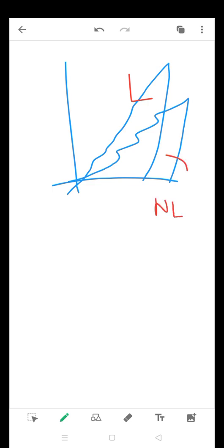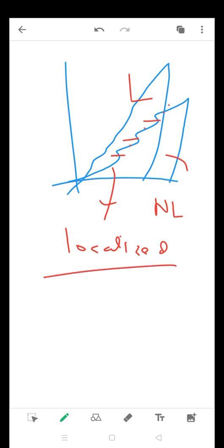So the difference that you can see between the two plots is that there are many more discontinuities or many more steps observed in the non-layered one, and these steps correspond to localized fracture that has taken place while the indent is being penetrated through the sample. Comparatively, the localized fracture is much less in the case of a layered SSC. That makes the layered one more stable compared to the non-layered one. That's the first thing. Secondly, there is another parameter.